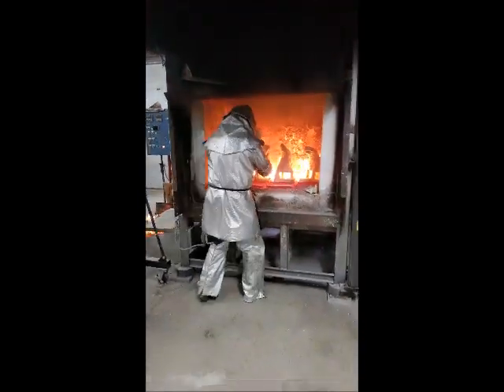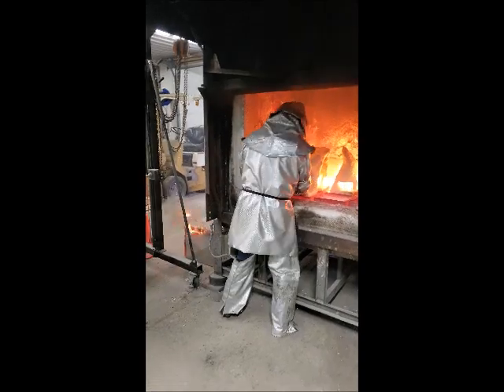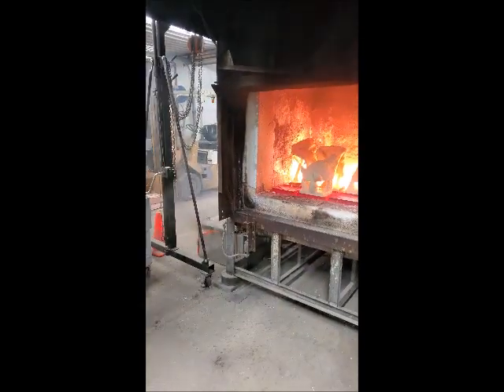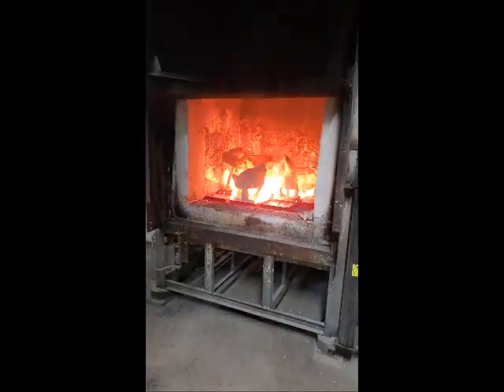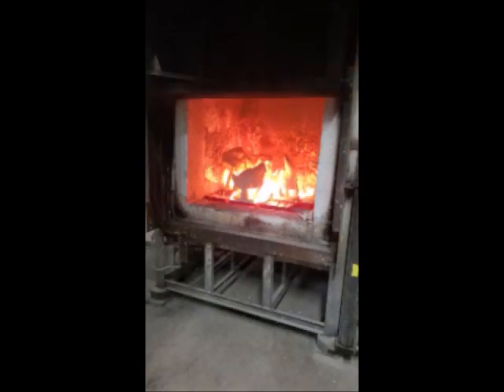The wax replica, which is covered by silica shell, is placed in a kiln and is fired at 1,650 degrees Fahrenheit. This rapidly melts out the wax, fulfilling the lost wax title, and leaves a 3/16 inch hollow cavity that was previously occupied by the wax replica. The wax gates and vents and base are also melted out. The hollow cavity will eventually be occupied by bronze.